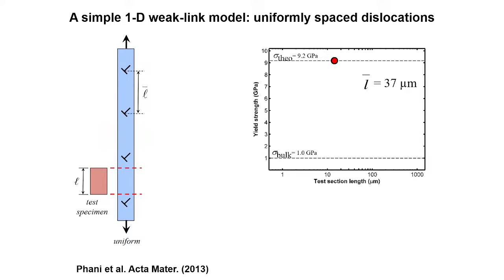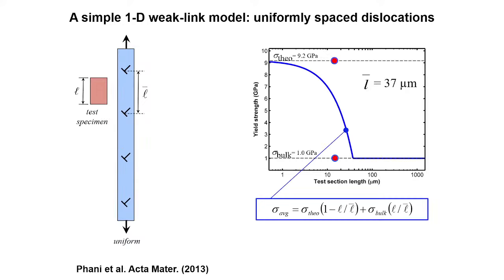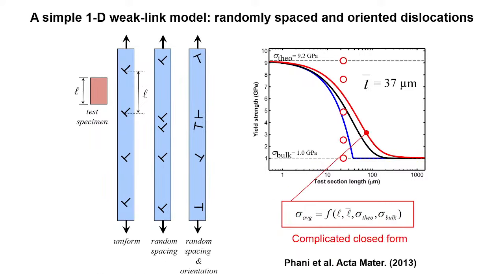But these don't have to be distributed uniformly. There could be a Poisson distribution, right? And this is what Pani did next. And then this is the solution to the Poisson distribution. I won't go into the details. And now you could add one more complication. In addition to a Poisson distribution of dislocations, you could give each dislocation an activation strength, right? Each dislocation moves only when you apply a certain stress to it, right? And so this is a combination of random spacing and orientation. This one, unfortunately, doesn't have a closed form solution, but you can get a numerical solution to that, and that's what this looks like.